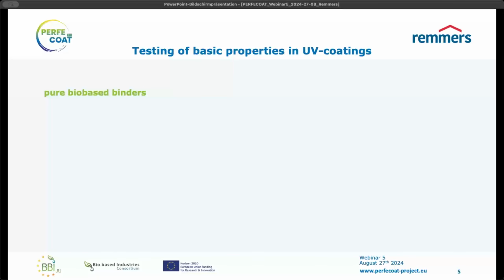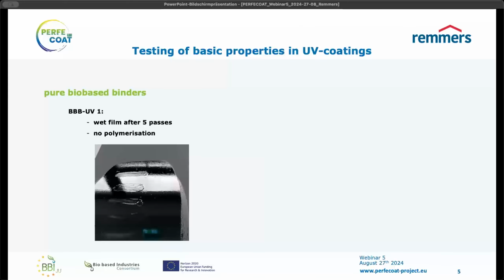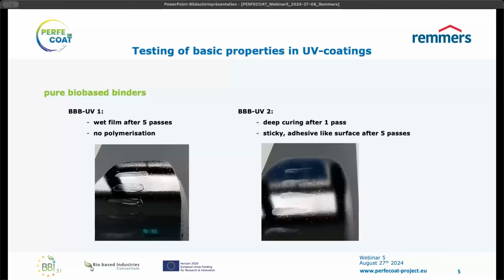So let's look first into the pure bio-based binders, of course mixed with some photoinitiator to initiate the reaction. Here we see binder number 1, and unfortunately, even after 5 passes under the mercury lamp, we still had a completely wet film, so there was no polymerization happening at all. The bio-based binder number 2 was looking quite different. We had a good deep curing already after 1 pass under the lamp, but to our surprise, even after 5 passes, the surface stayed very sticky, almost like an adhesive surface.